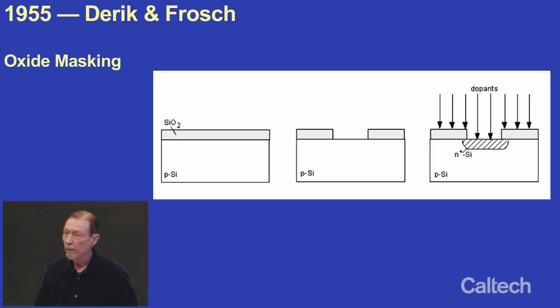And then I use a photolithographic process, which is well known from the printing industry. And I cut a hole in it with hydrofluoric acid. You can dissolve silicon oxide with hydrofluoric acid and it won't attack the silicon underneath, so it stops at the right place. And then I apply some of the impurity atoms and I heat them up and they diffuse in, and I've just made myself a junction right where I want it. And I didn't have to have jets of stuff and deposit things hanging out in the air. This was just on a surface of silicon.